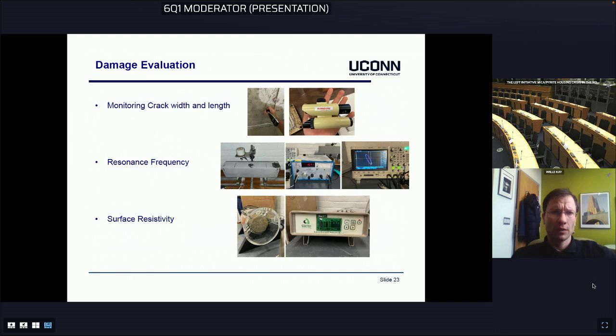We also evaluate damage with different methods. For example, we monitor crack width and crack length. We are currently exploring using resonance frequency to evaluate the damage inside before it becomes visible, and also surface resistivity, which is an indication of the pore structure and the pore quality of the concrete. Next slide.